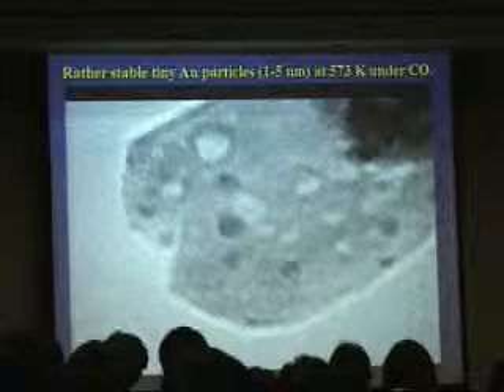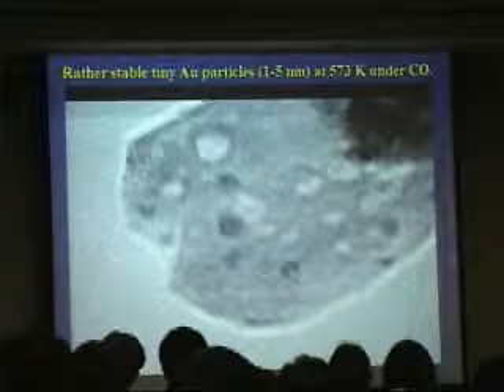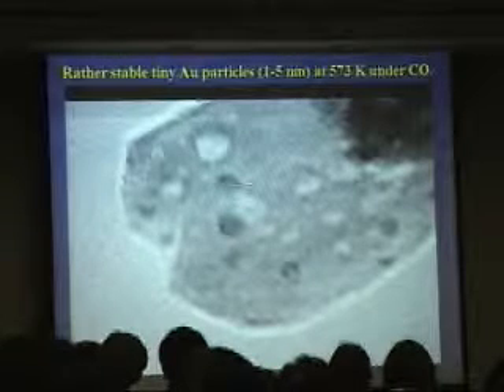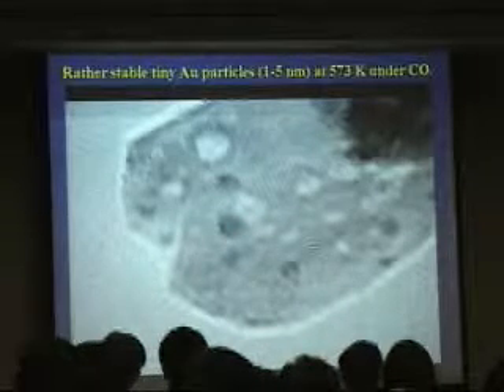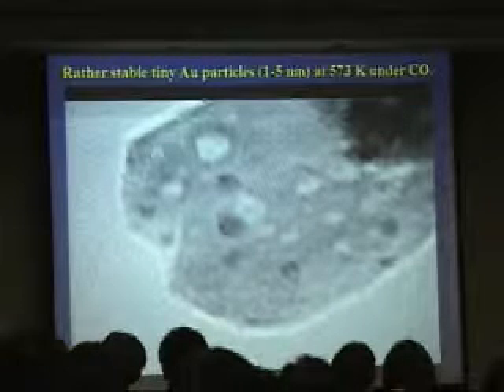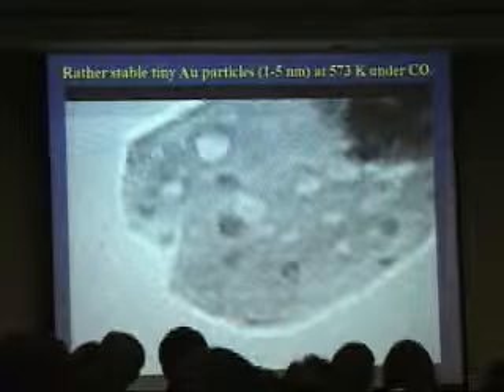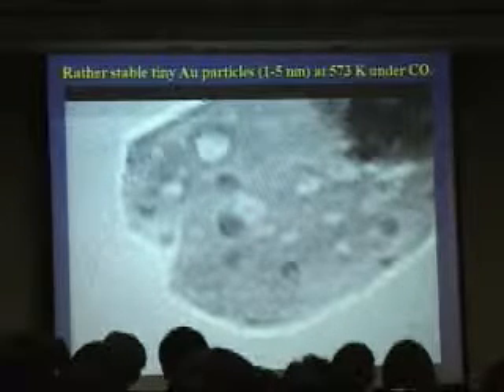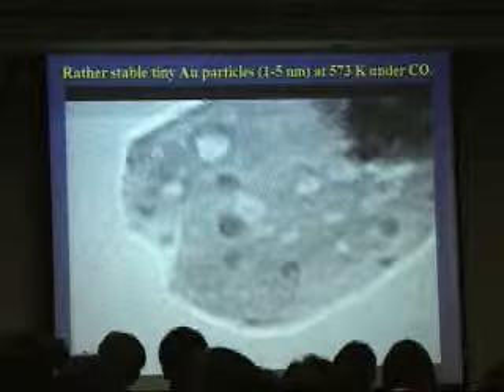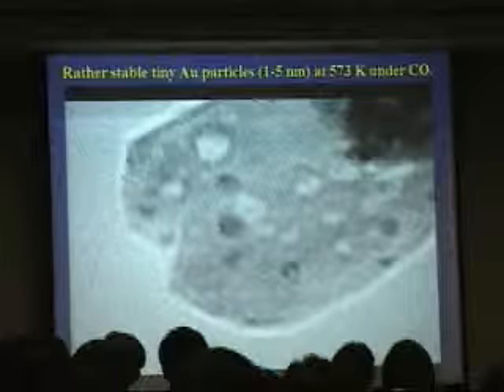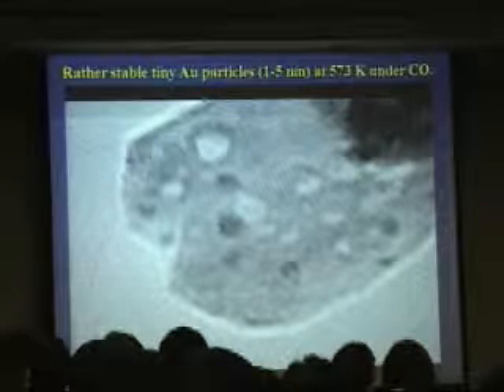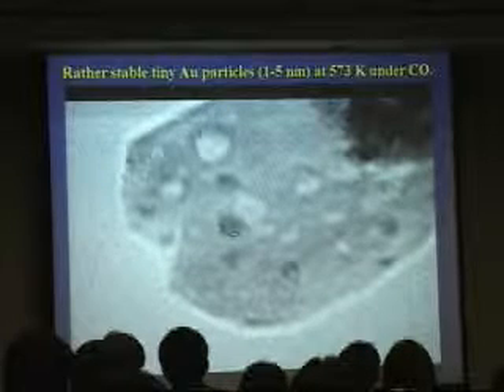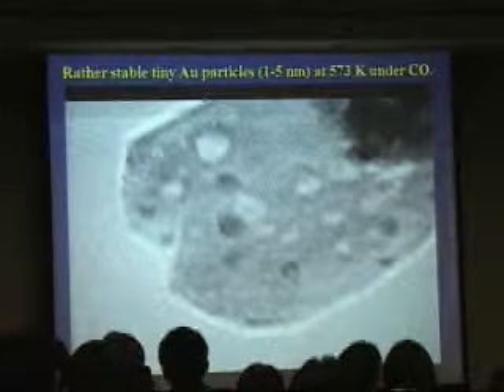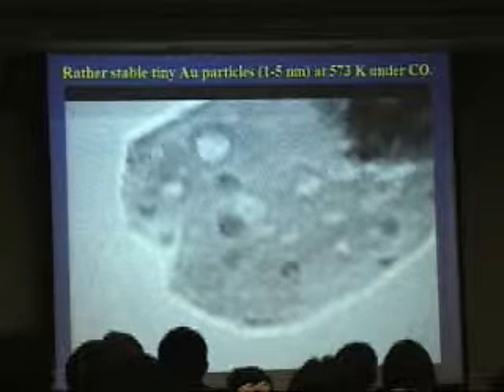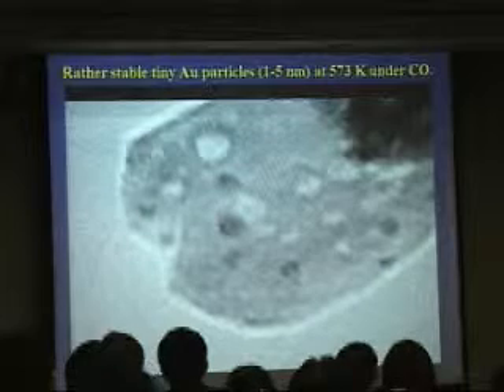And how strong it is, I can show you very briefly under very severe conditions. So this is the gold particle, this is the rod-shaped ceria support, and we put this sample in an environmental TEM and heat the sample to 300 degrees C with an atmosphere of carbon monoxide. And we want to see whether gold rapidly aggregates into larger particles or still keeps rather small particles. So in this case, from this 2 nanometer scale, you can find those particles are about 2 nanometers, 1 nanometer, even some half-nanometer particles, even under these very severe conditions.